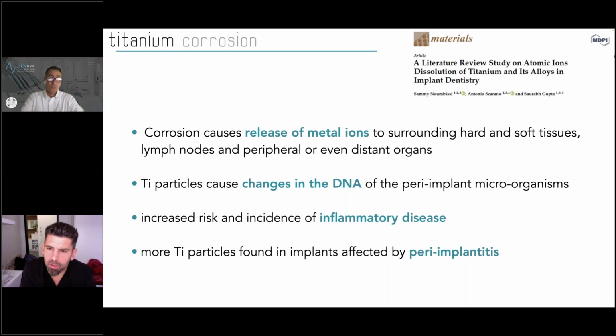Obviously, titanium is a metal, and metals corrode, and corrosion can cause the release of metal ions to surrounding hard and soft tissues, lymph nodes, and peripheral or even distant organs. Studies show that these titanium particles can cause changes in the DNA of the peri-implant microorganisms, and there can be an increased risk and incidence of inflammatory disease. And actually, studies show that there are more titanium particles found in implants that are affected by peri-implantitis. There are several studies that compared healthy versus not healthy implants affected by peri-implantitis, and they saw that there's a higher concentration of titanium particles in these implants.